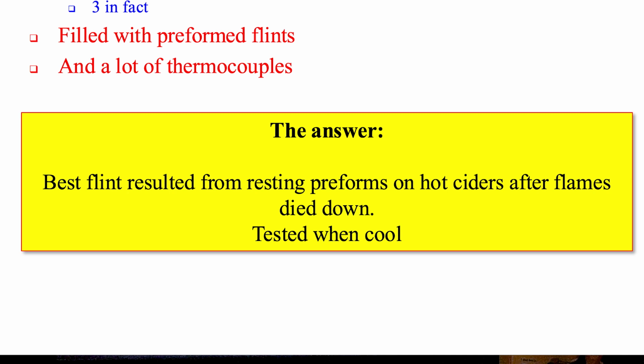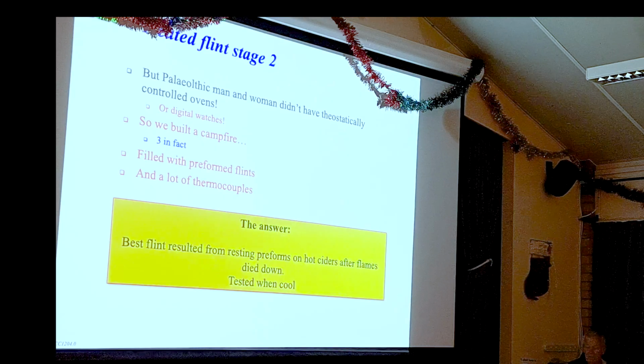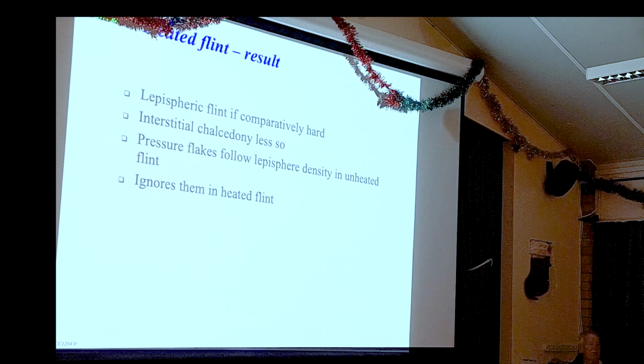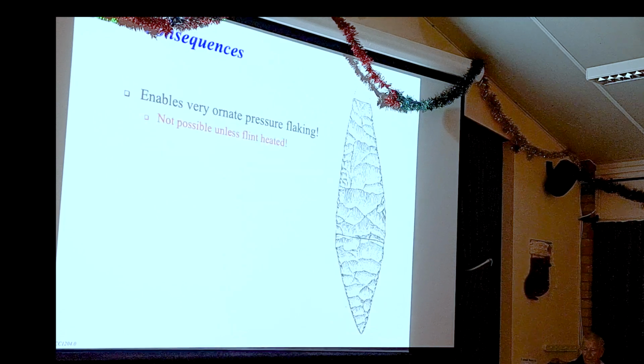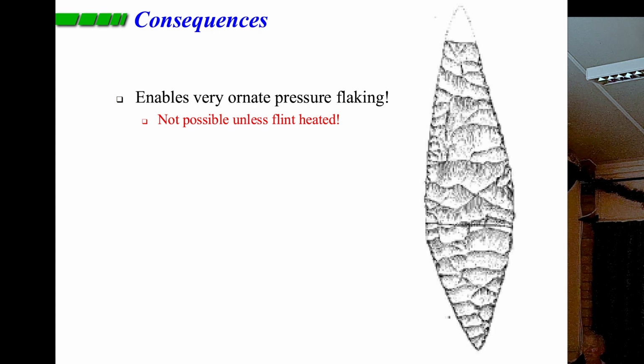And we then had to leave them in the yard with instructions to the cleaners not to clear up after us. But it turned out this gave us quite a significant impact on the flint structure. What's happened essentially is this: lepispheric flint is quite hard in comparison with interstitial chalcedony. When we homogenize the structure, the fracture would ignore these clusters of lepispheres and give you a much more predictable pattern. And the result of that is you can make very, very ornate artifacts.